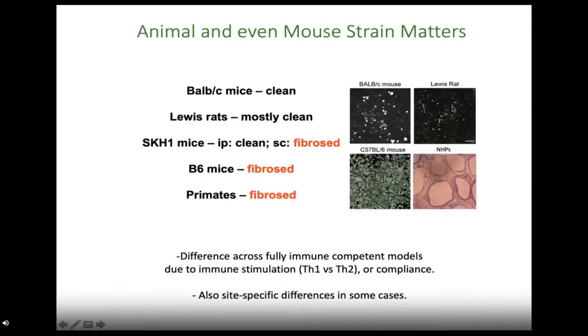Here's an example of clear translucent hydrogel spheres that we place in these animals. In the Black/6 mice, all of them are very apparent visually — they're individually all fibrosed, with a white-yellowish appearance from immune cell aggregation and extracellular matrix deposition on the surface. In BALB/c mice by comparison, very few show fibrosis — most are still clear and translucent. In Lewis rats, you see even less fibrosis.